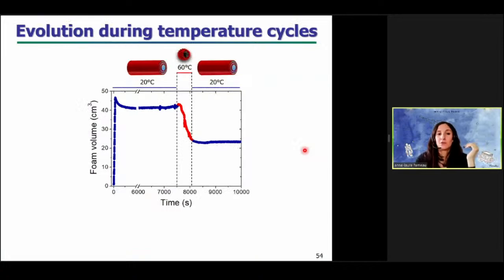So then we decided to see what is the evolution of the foam stability during temperature cycles. For this, we just produce foam by bubbling gas into a tube solution until a fixed volume of 45 milliliters is reached. And when the temperature is at 20 degrees, tubes are present inside the foam. The foam volume remains constant with time, as you can see here.